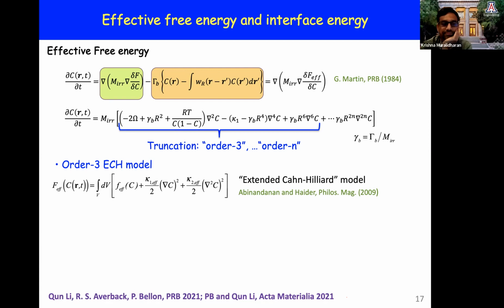Yeah, this simple concept has its limitations. For instance, you might predict why a precipitate will dissolve under plastic deformation or irradiation, because if you look at the phase diagram and raise the temperature high enough to cross the solubility limit, you will be in the single phase region. So that's consistent with dissolution, the disappearance of precipitates. However, there is no nanostructured microstructure in an equilibrium phase diagram. So self-organization cannot be captured by that effective temperature criterion.